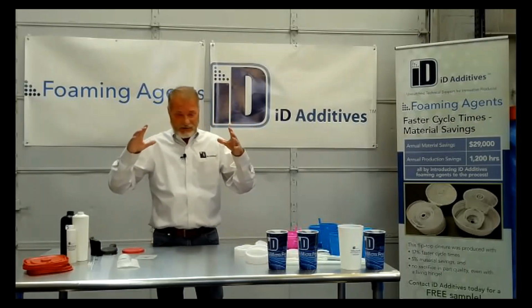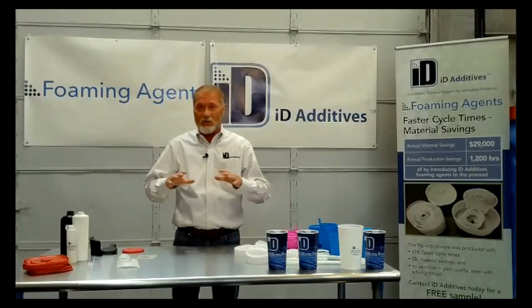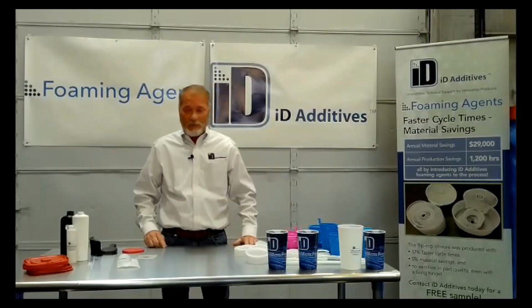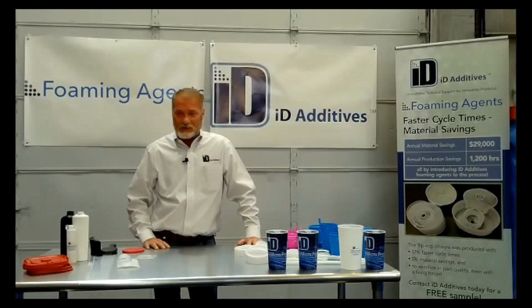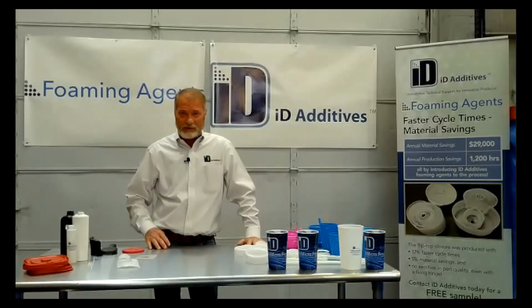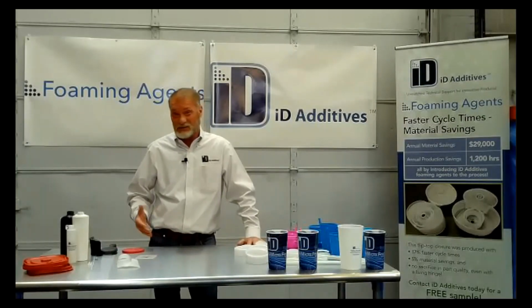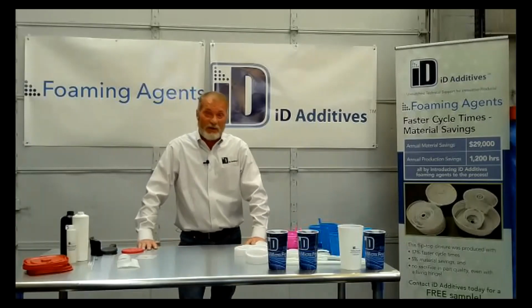It's really easy to blow it out at that point. So keep in mind those pressures. Typically, I run about 30 to 35 PSI. I've gone as high as 39, but if you're doing 40, 50, 60, up to 90, usually it's 90 PSI, you're not going to see anything.